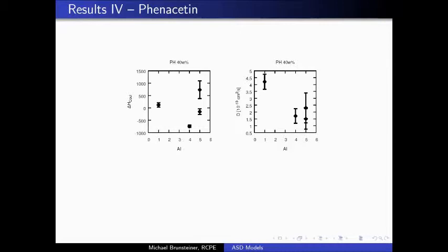So we've got basically one compound that's much less stable than all these 3 others here, and this has a much higher mobility in the matrix, which means that it's faster in getting to the equilibrium structure, and the equilibrium structure is the crystal, or actually the phase separated state, and therefore this guy here is less stable. So this makes sense.